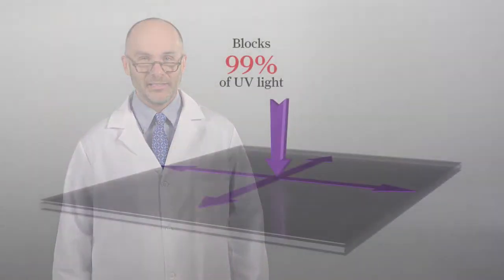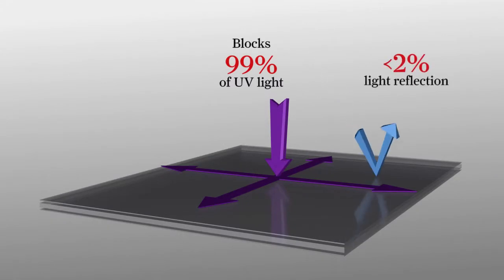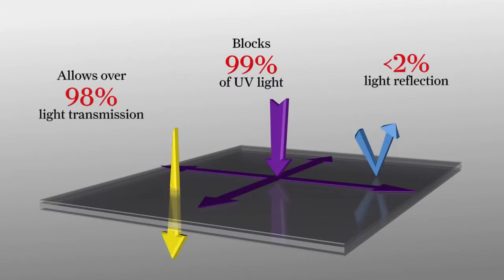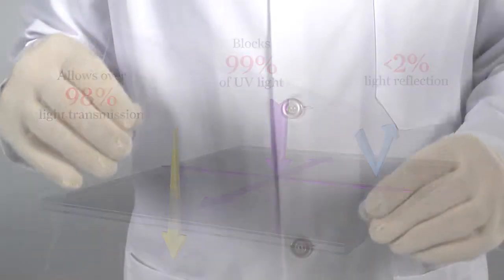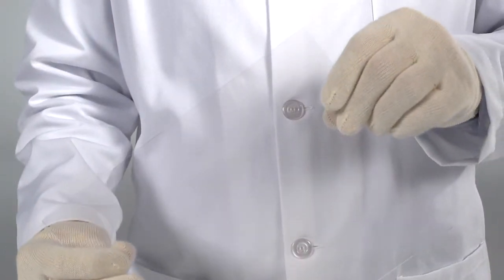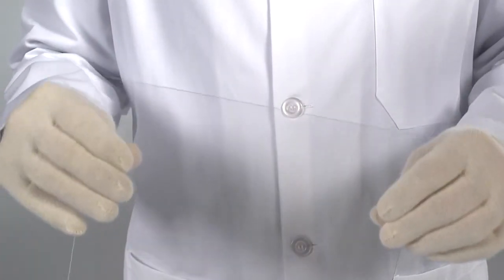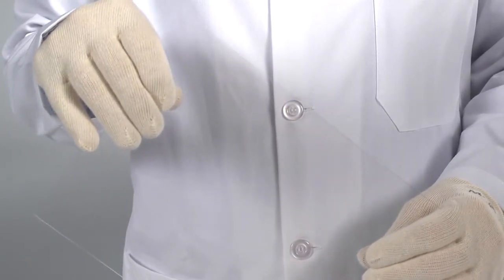They worked hard on this. The coating is engineered for demanding optical requirements, durability, and strength. With less than 2% light reflection and over 98% light transmission, you see why Optium Museum Acrylic is the optimal choice in glazing. It offers up to 20 times more protection than regular acrylic and resists minor scratches associated with frequent cleaning.